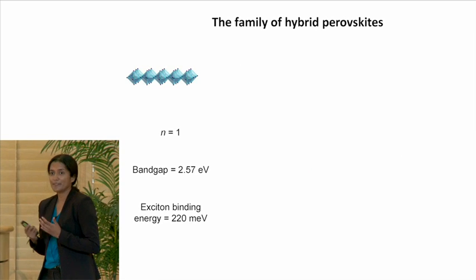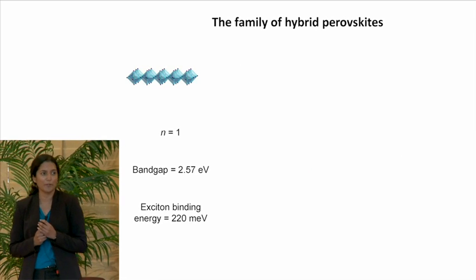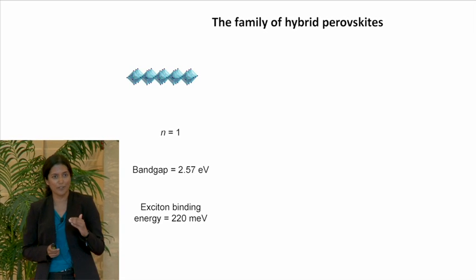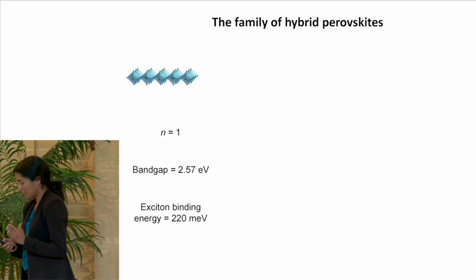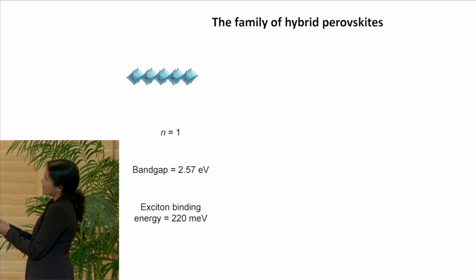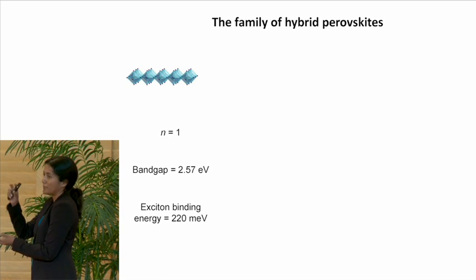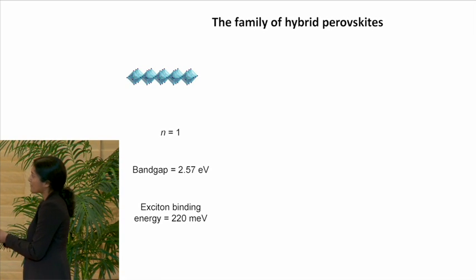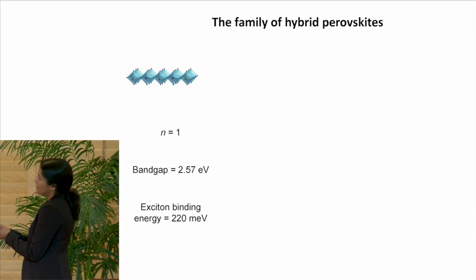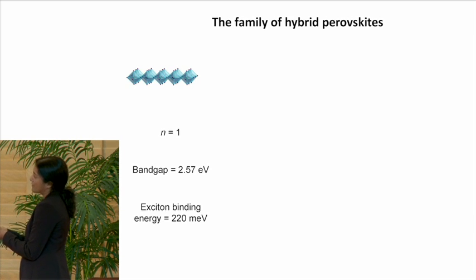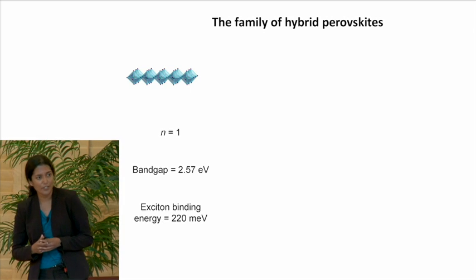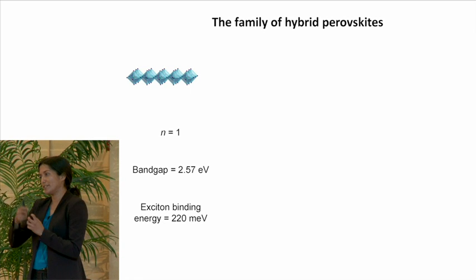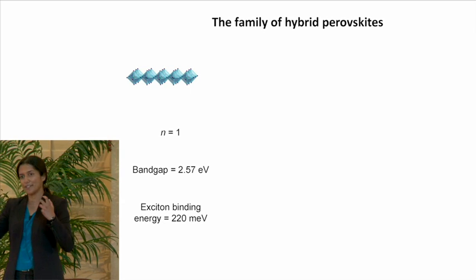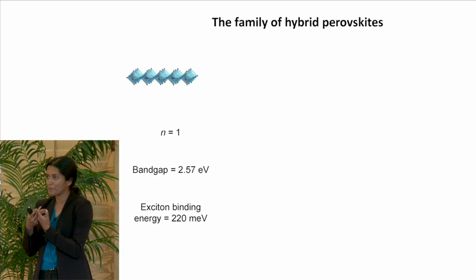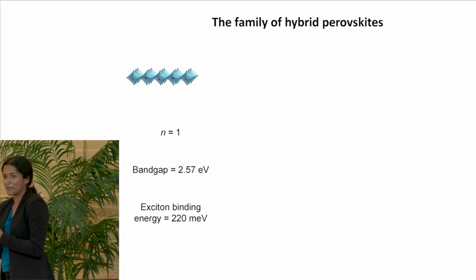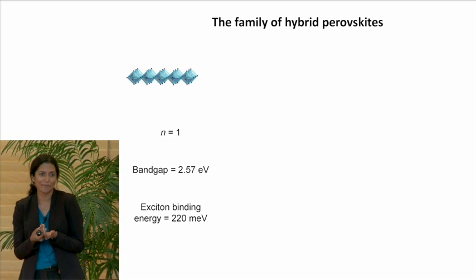So in my lab, prior to our work on solar cells, we had been working on the layered perovskites that I showed you in one of my first few slides. These materials have just one inorganic sheet sandwiched by organic layers above and below, and this is a repeating unit. And I'm going to call this n = 1. This has a very large band gap, and this has very high exciton binding energies, which means when you hit this with light and you generate electrons and holes, these charge carriers are very strongly attracted to each other. In fact, these have all the properties that you seek to avoid in a solar cell absorber.